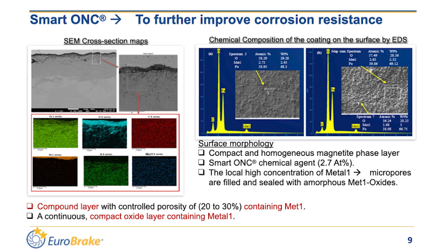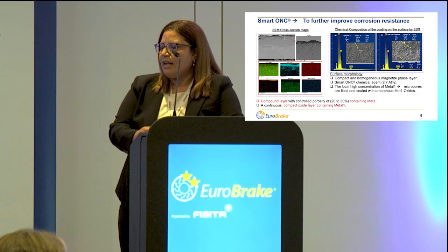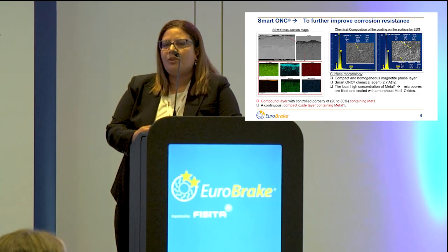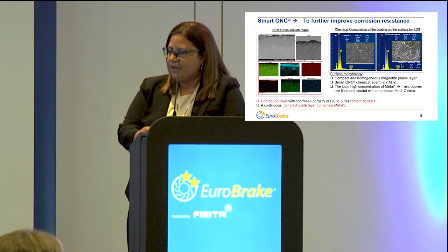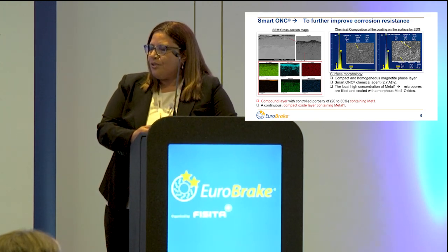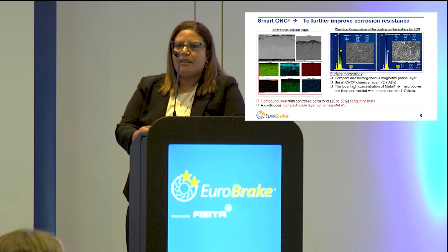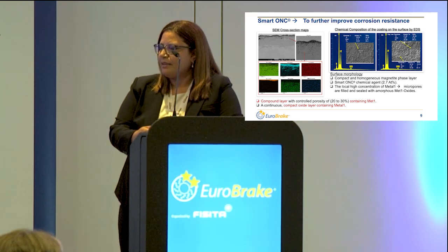a chemical agent. With scanning electron microscope cross-section maps, we can see that we have formed a compound layer with about 20 to 30% of porosity, which was controlled, and it contained metal 1, which is the Smart ONC chemical agent. And also a continuous and compact oxide layer that also contains metal 1.